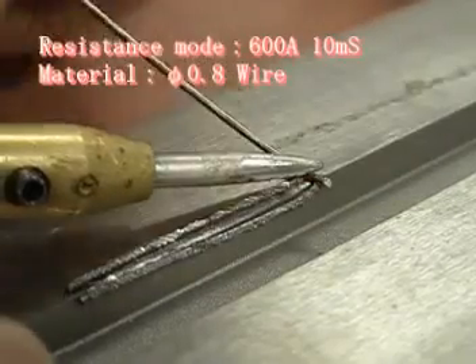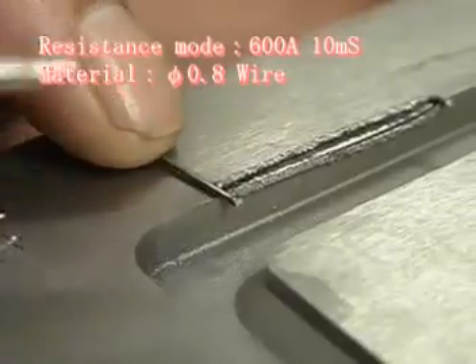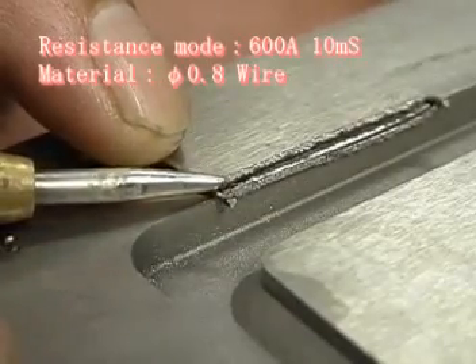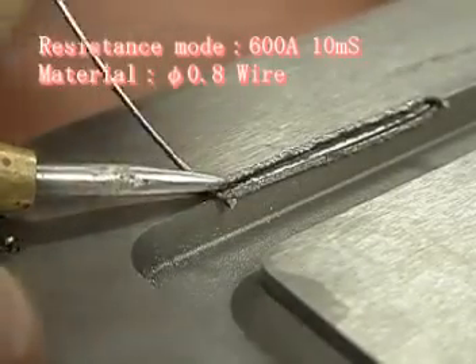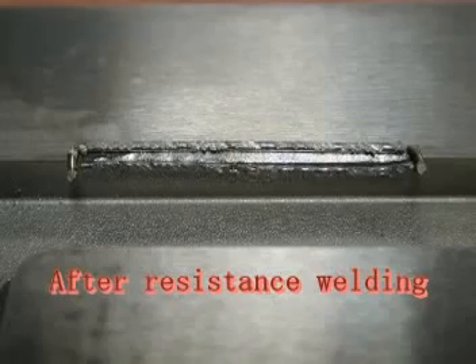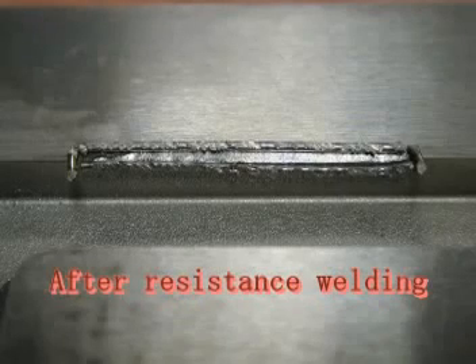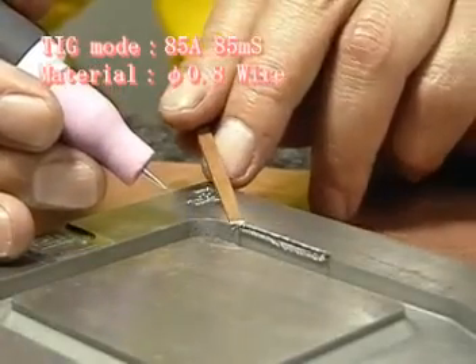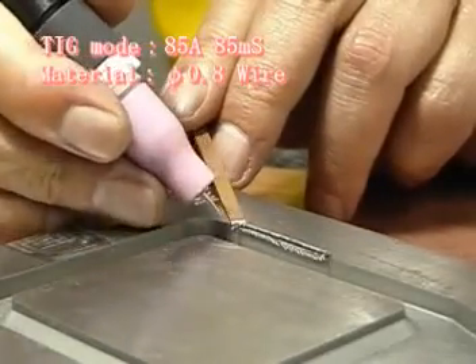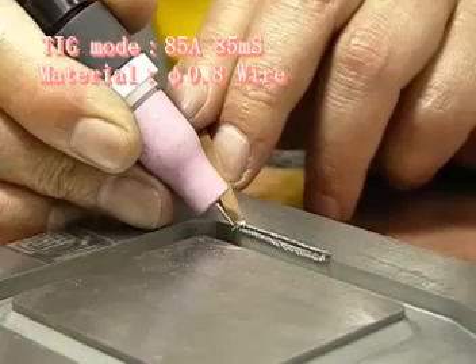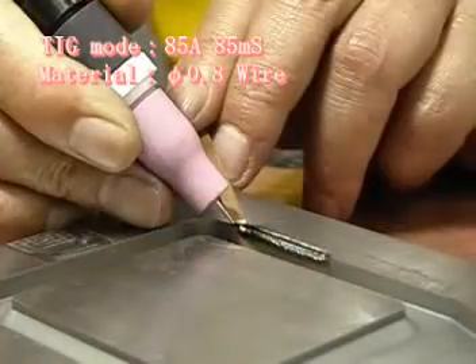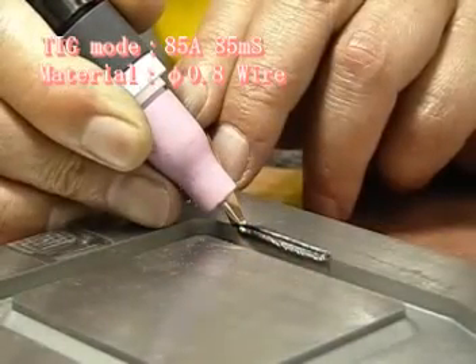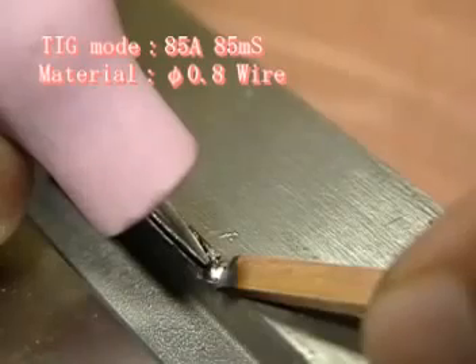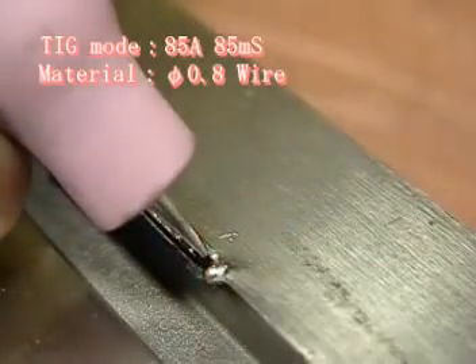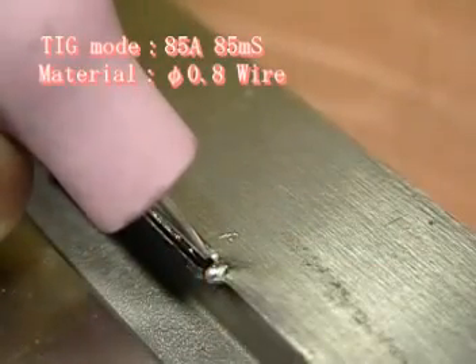Then place wire materials in a lengthwise direction on both sides to avoid shrinkage. Fix wire materials temporarily in this way. Next, weld using the TIG mode. Start melting the material from both ends and apply a copper plate to absorb excess heat to avoid shrinkage. Make a clearance of around 1.0 mm between the electrode and the welding material.